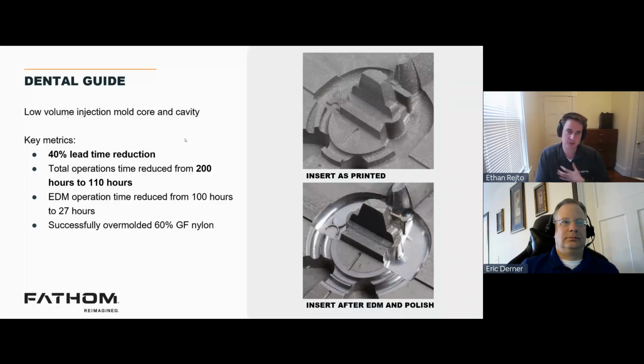But even though they were touching those features up, they still saw a 40% lead time reduction, 200 hours of operations down to 110, and removed EDM operations from 100 hours down to 27 hours.